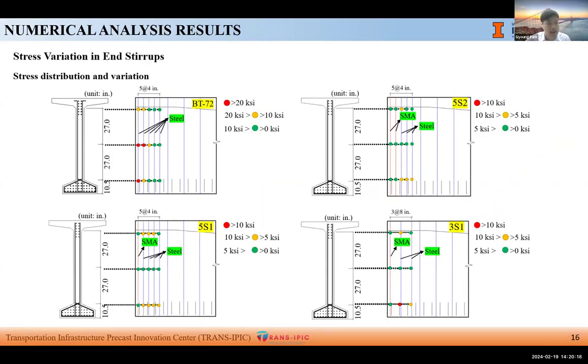Finally, by inspecting stress distribution and variation within end stirrups, the variation of stresses with SMA models were mostly below 10 KSI. The maximum stress variation was at 3S1 case with 10.4 KSI due to its large spacing of 8 inches. Still, the value was under 20 KSI and even lower than stress generated in BT72 model in equal locations. As per AASHTO codes, the demand of stirrups at the end region can be reduced with using SMA stirrups.